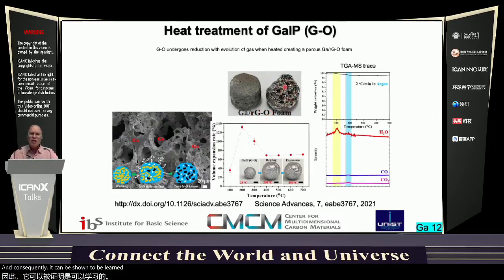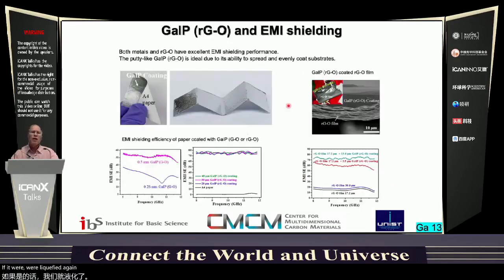Chunhui learned, he can take this material and knead it, press it again, and make a putty over. So although this material is brittle and has these large cavities, by working it some more, you can convert it back to a putty, but now you have reduced graphene oxide rather than graphene oxide. You have what we could call graphene in essence and dispersed inside of the liquid metal if it were liquefied again. So we were able to show in our work that this had particularly effective EMI shielding. And I'll come to thermal properties as well, which were very, very promising. So it can be readily spread on paper. It could be put onto, as a thin layer, onto a film composed of stacked and overlapped RGO sheets. And the EMI shielding was very effective over this range from 8 to 12 gigahertz, for example.